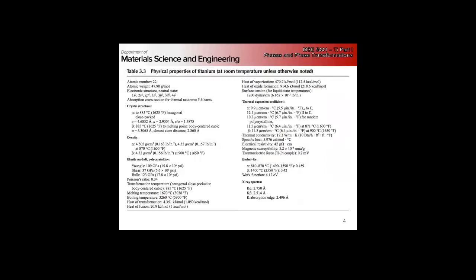Right? So it's 60% of the strength of steel, about 50% more than aluminum, right? But a density that puts us, in terms of strength per weight, significantly higher than most steels, right? So where does that tell you we're going to see a lot of application? What's that? Yeah, right. Anything that we're concerned about efficiency, right? So aerospace, automotive.